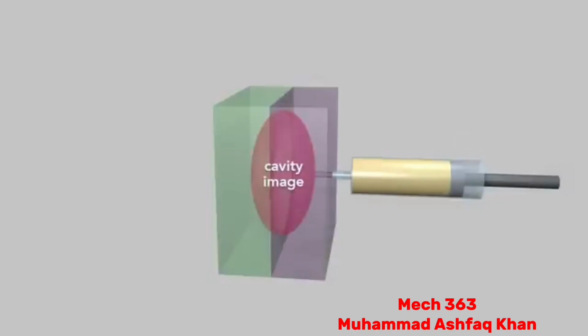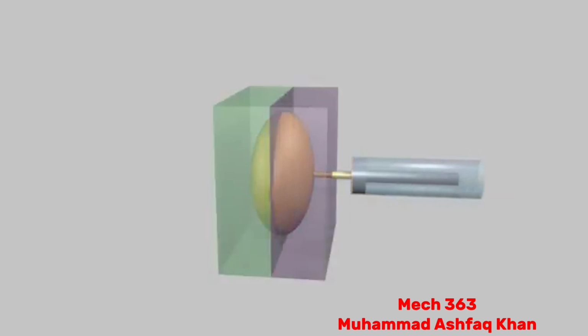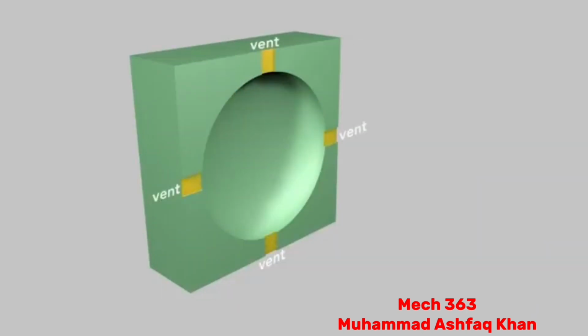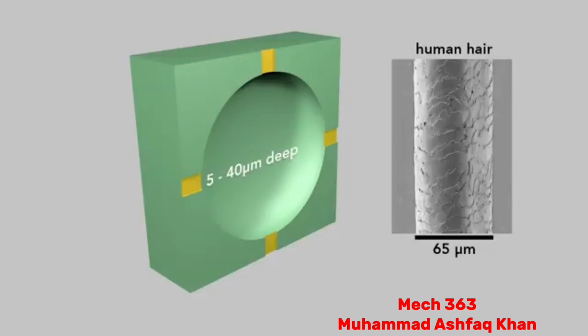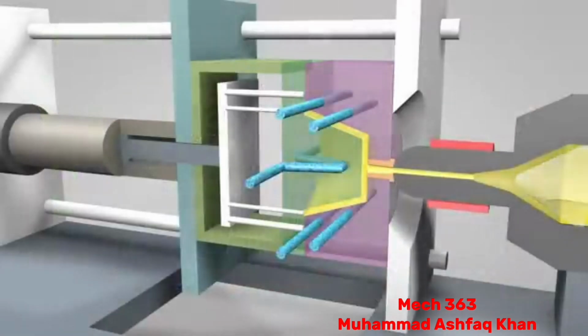Initially, the cavity is filled with air. As the molten plastic is injected, it forces air out of the mold, which escapes through vents. These vents are channels ground into the landing surface of the mold. They're very shallow, between 5 and 40 microns deep. The plastic, which has the consistency of warm honey, is too viscous to flow through the narrow vents. Typically water flows through channels inside the mold just beneath the surface of the interior.